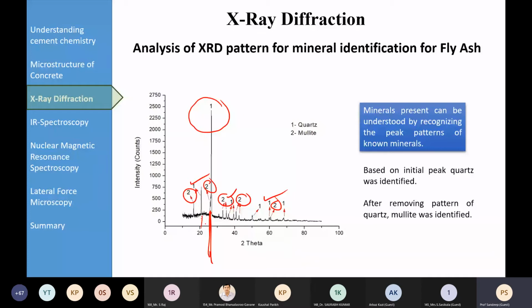So minerals present can be understood by recognizing the peak patterns of known minerals, and based on initial peak, here the quartz is identified because this is quite a high peak, and this is basically a relative intensity count. Next time it may be 3500, doesn't matter, but it is a relative count of 1:2. Absolute values are not important. What is important is relative intensity.